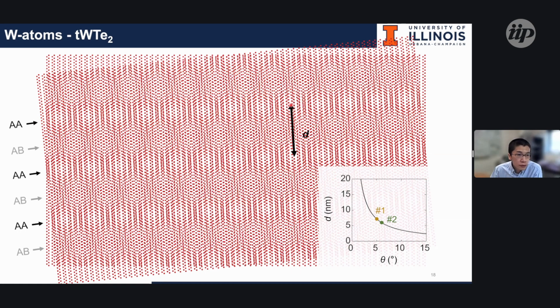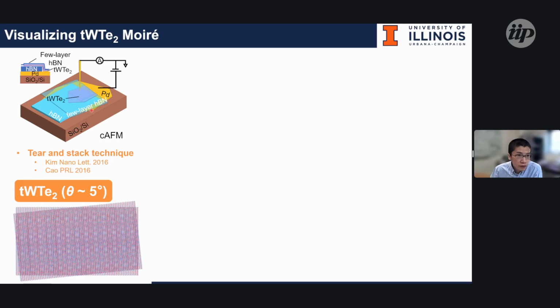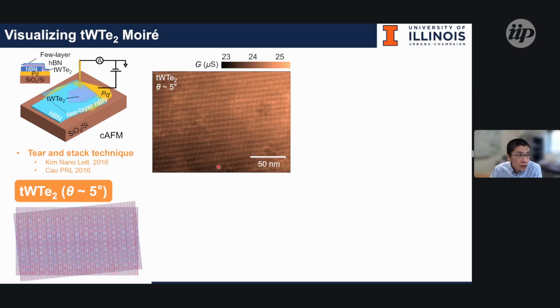This is work I did in Princeton with colleagues, where we used a thin layer of hexagonal boron nitride which covered the twisted tungsten ditelluride. With this, we can touch it down to the palladium metal, and then use a tip at room temperature to image the Moire system.